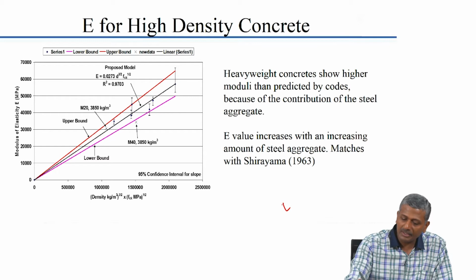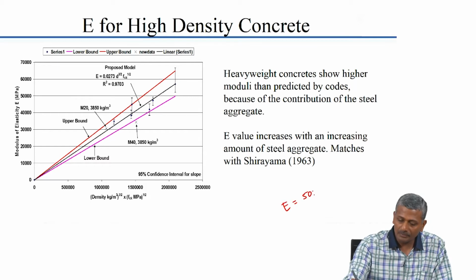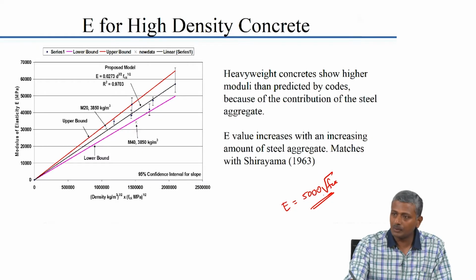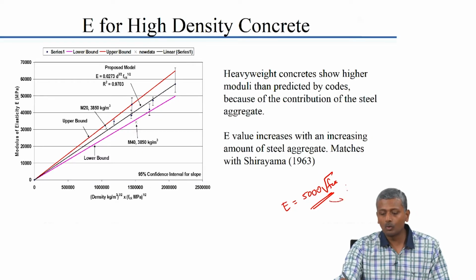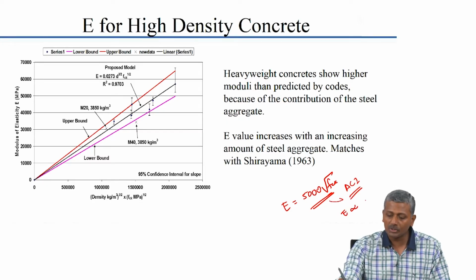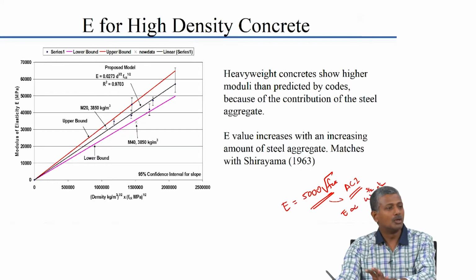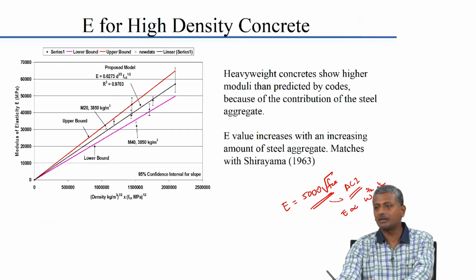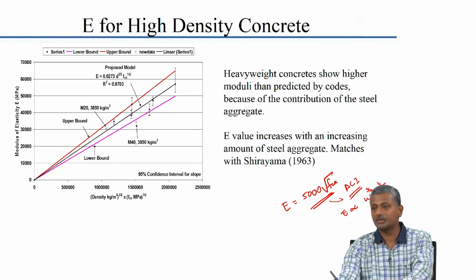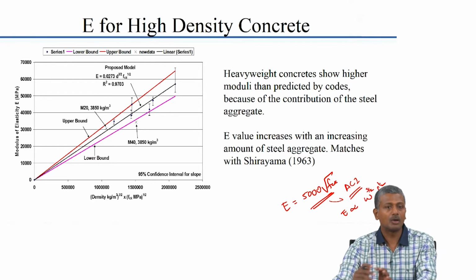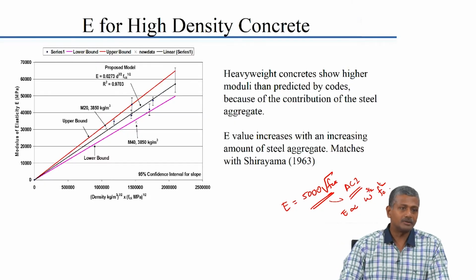For normal density concrete, we typically assume that the modulus is equal to 5000 square root of fck. Now, if you go into the basis for determination using this kind of an equation, this is derived from an old ACI standard where the modulus is seen to be directly proportional to the density of the material to the power of 3 by 2 and strength to the power of half. Again, there is no science behind this relationship; it is an empirical relationship that has been derived from large data sets that have been collected by researchers.